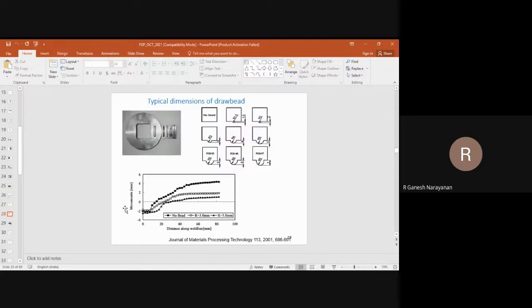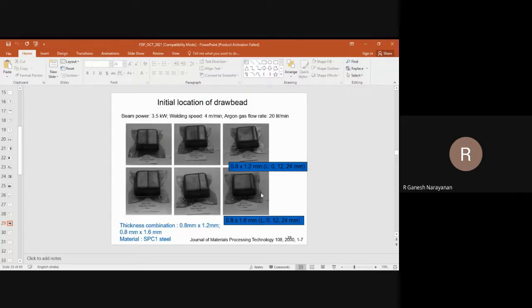And you can see the movement on y-axis is given, 0, 2, 4, 6 mm. You will see when you don't have bead at all, movement is more significant, almost like 5 mm movement is there. But when you have a larger draw bead of 5 mm radius, movement is restricted on the thinner side, because on the thicker side you don't need it because it's anyway stiff. Location of draw bead, correct.